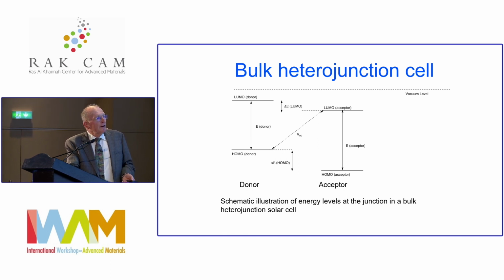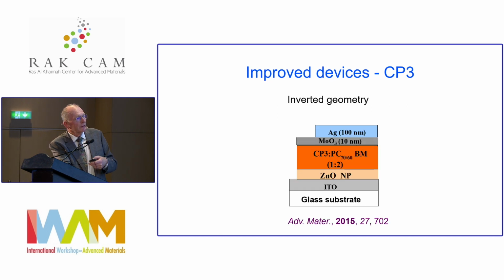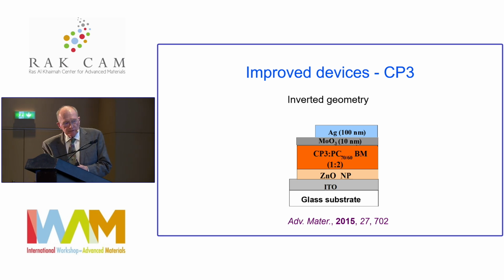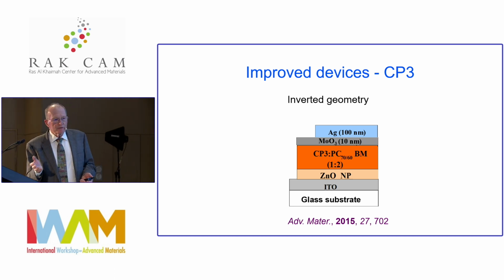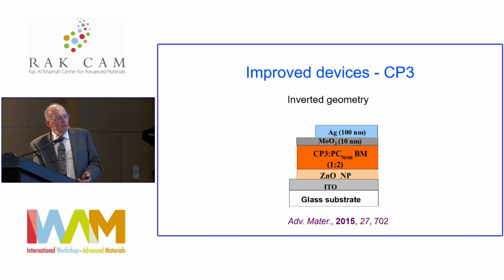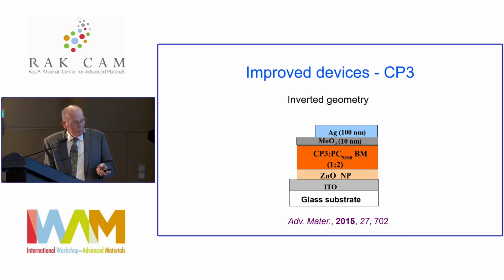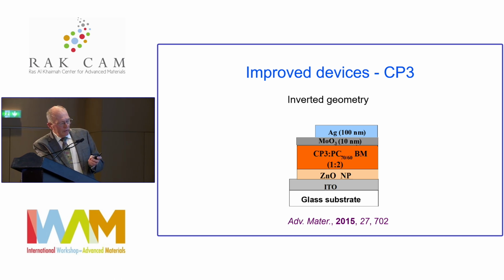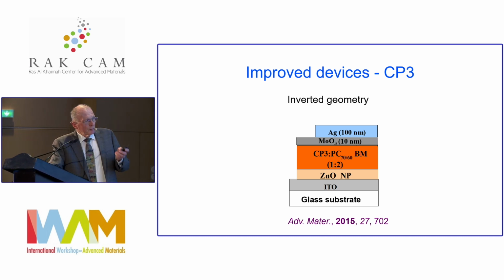So that's the challenge. And where should I point this? Towards there? Or there? So I want to talk about the best device we got in that consortium at the time, and that's the so-called inverted configuration. This is ultimately for deposition facilitation. It's much easier to work from the bottom up in the way I've drawn this slide. So indium tin oxide, a zinc oxide nanoparticle, which makes that behave as a cathode. The blend of a very good polymer that was designed in the collaboration with the accepting fullerenes, and fullerenes were in the early days the dominant charge accepting material, so a blend of the donor polymer and a derivative of a fullerene, C60, C70 combination. Molybdenum oxide to help the interface with the cathode, with the anode at the top, sorry. So that's the way in which it worked.